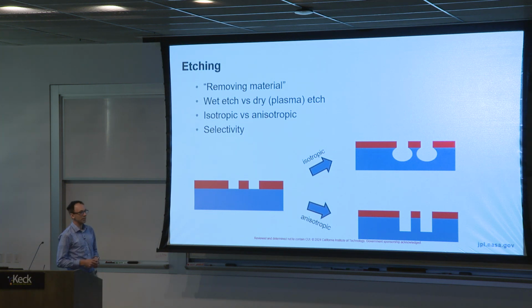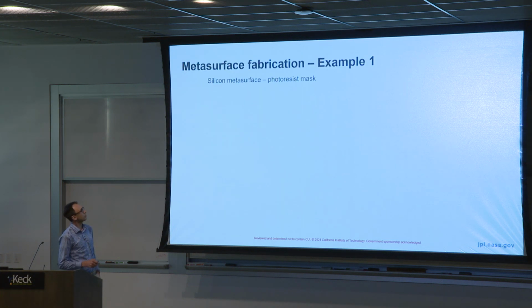And selectivities can range widely. You can have a selectivity that's lower than 1, meaning that you etch your mask much faster than you're etching your actual material. That's not the ideal case, but it does happen that you find yourself in a situation where you need to do that. But typically you have selectivities of maybe 50, 100, even several hundreds. I've even seen papers where they claim that they have 70,000 as a selectivity. So you then need almost no mask at all to actually perform your etching. So that's an important consideration when you're setting up the entirety of your process.